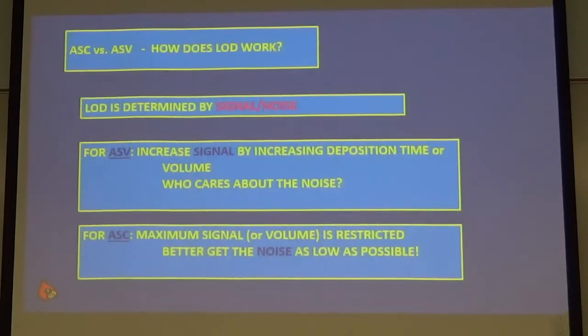Well, there's an old, long-standing analytical technique called ASV, or anodic stripping voltammetry. When you deposit a metal by reducing, then you strip it off by oxidizing it. That's called anodic stripping. That's what we're doing. The traditional way of doing that is to apply that potential for a long time. So you deposit for a long time. And while you're depositing, you can flow or stir your solution. So in anodic stripping voltammetry, you get down to very low concentration levels because you can deposit for a long time by using a lot of volume of sample. In our case, we can't do that.